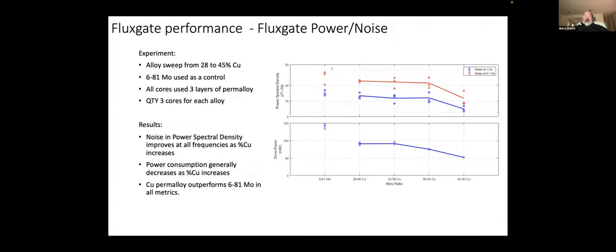The dots here are the noise power spectral density at 0.1 hertz and 1 hertz respectively in red and blue for the 6-8% moly legacy material here, and then the four copper materials we tested, starting with the 28% copper and going up to the 45% copper. First thing to note is that all of the copper alloys that we chose to test are quieter than the legacy material. Further, as you go from 28% up to 45% copper, it gets quieter, both at 0.1 hertz and at 1 hertz. And the numbers down here are just our record setting low noise. These are just a few, you know, 6 picotesla per root hertz for such a small sensor is pretty record setting.